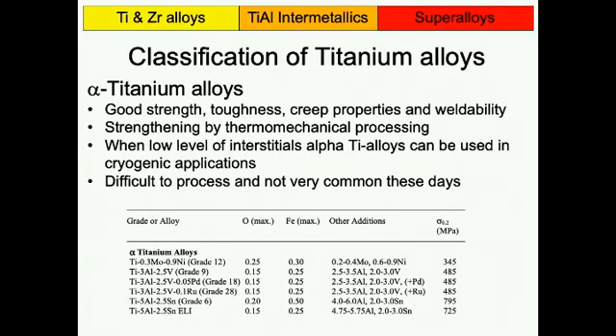That's right, closely packed and not closely packed. Remember when we discussed diffusion rates? So creep is very much a diffusion controlled process. If you have a crystal structure which is closely packed and has low diffusion rate, you end up with better creep properties. And by having some noticeable amount of beta phase in the material, you might actually deteriorate the creep properties of such a material. That's why creep properties are mentioned here, because apart from a very, very tiny amount of beta phase to mop up nitrogen, you don't really have any beta phase here. And so that can be beneficial.